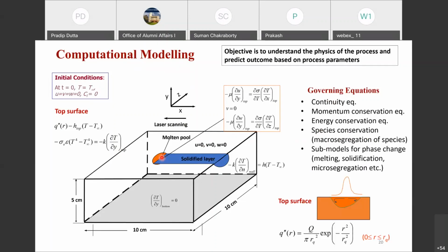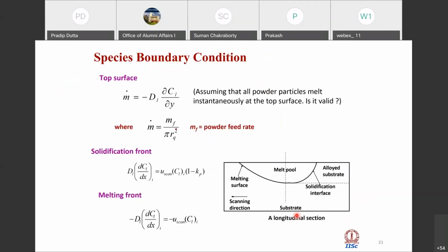Okay. And of course, the top surface is modeled in the same way as far as heat distribution is concerned. So I'm not going to repeat that. So a little bit about the species, because this is a moving pool. On the top surface, we have a species mass input. If this m dot is the powder feed rate, then this is how on the top surface, through a species gradient, we would model the rate at which the powder enters.